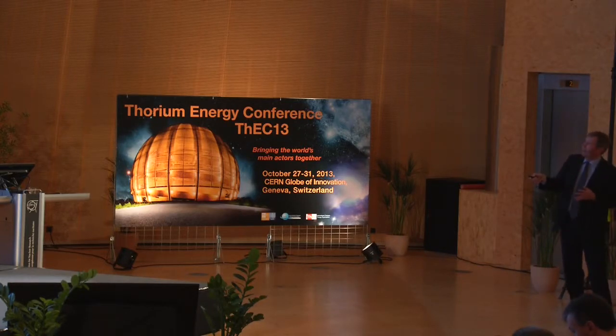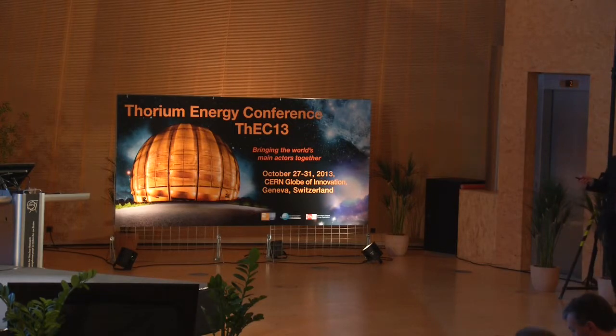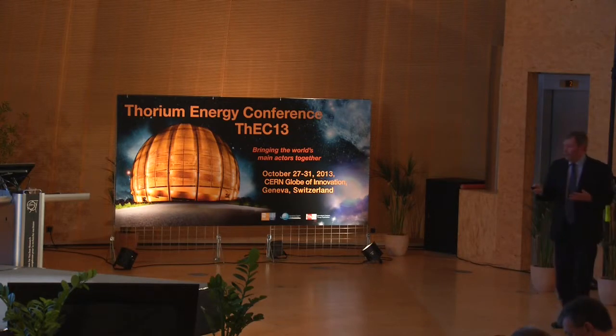So we have a phase diagram here which is constructed from thorium fluoride, cerium fluoride. And by combining these elements within a thermodynamic model, and I stress it is a model, one can come up with predictions about solubilities of, for example, plutonium in these mixtures of different compositions. You can see appreciable variation. You can see these solubilities are not high, so this issue of plating out of plutonium in the heat exchangers here is a real one. You can see that the temperature dependence of the conductivities are quite high. So what I've got here are the predictions of these thermodynamic models, and here are some spot experiments which have been done at ITU in order to check that the model's working.